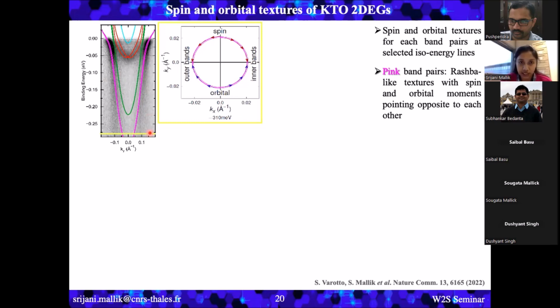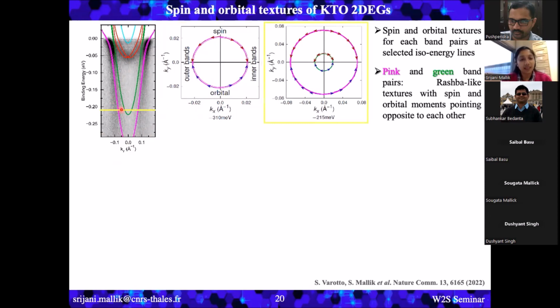So here I would like to define a nomenclature for all the images, because here in this image, let's say the top part contains information about spin, the bottom part contains information about orbital, the right part contains information about the inner bands, and the left part contains information about outer bands. And this kind of nomenclature I am going to use for every isoenergy line. So here at very low energy, we can only see one band is present and it's very nicely standard Rashba. Then as we increase the energy close to the band edge of the green pair of bands, this is also similar.